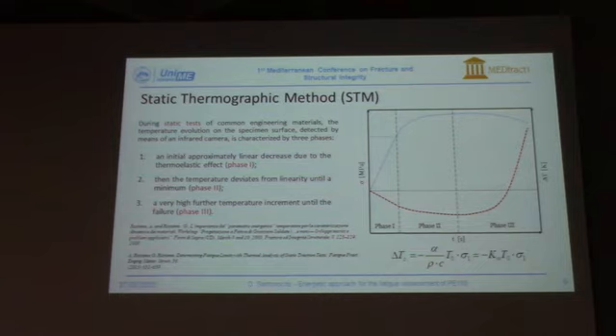The change in the slope from phase 1 to phase 2 could be related to a macroscopic value of the stress that introduces the first plasticization in the material. Hence, if we cyclically stress the material with this stress, the material will break.